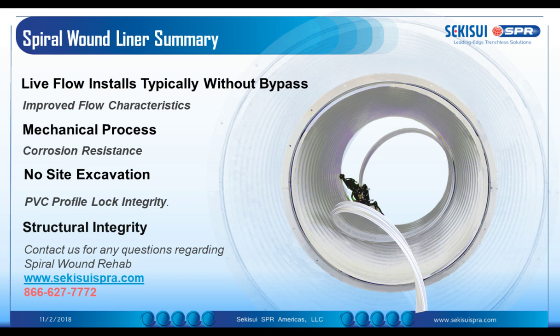It is driven by a few different things, such as the alignment and the amount of load back onto the equipment. There are ways to mitigate that load and reduce that load, but our experience has told us that at various diameters, such as an 8-inch liner, 200-millimeter diameter liner, I believe the maximum that we have done with SPREX is a little bit under 600 feet, for example.